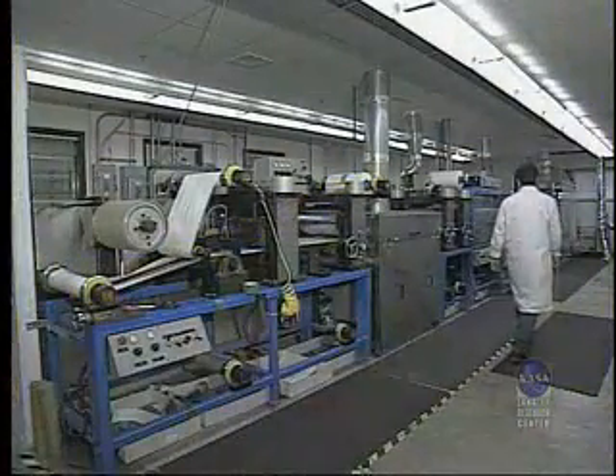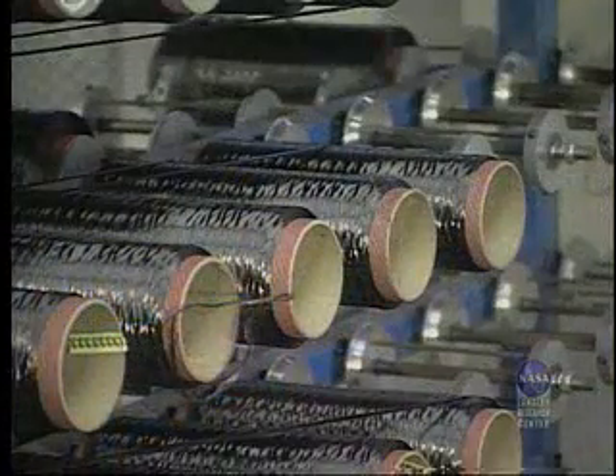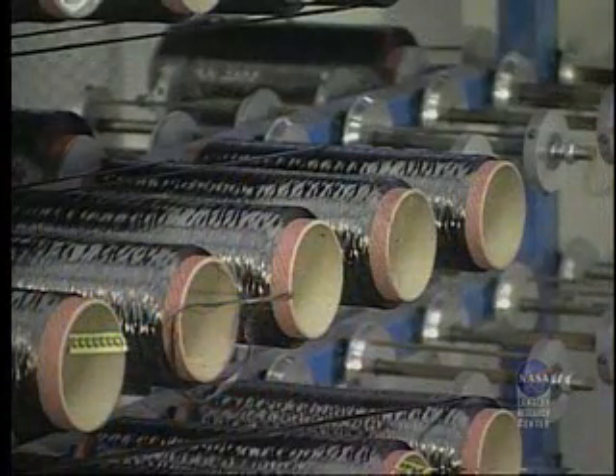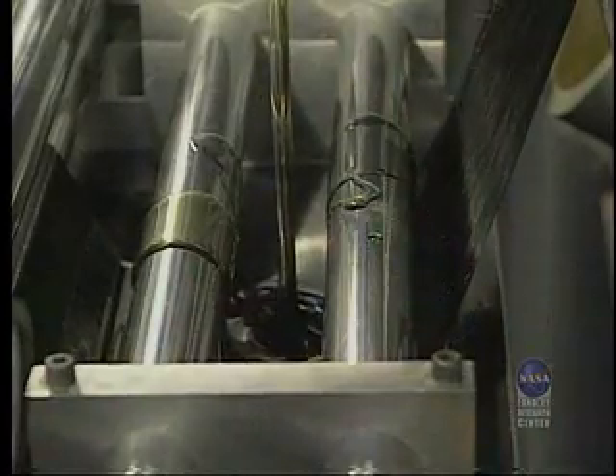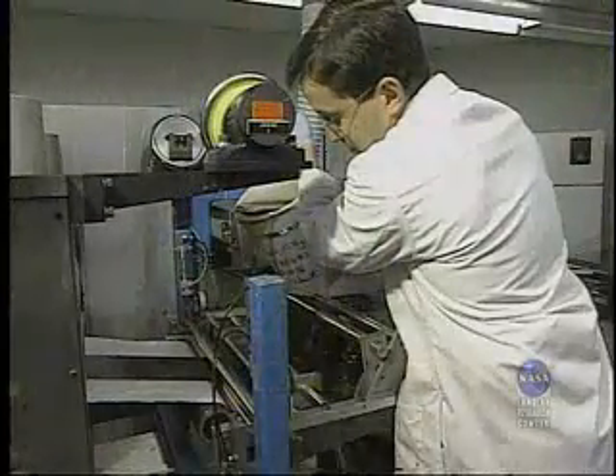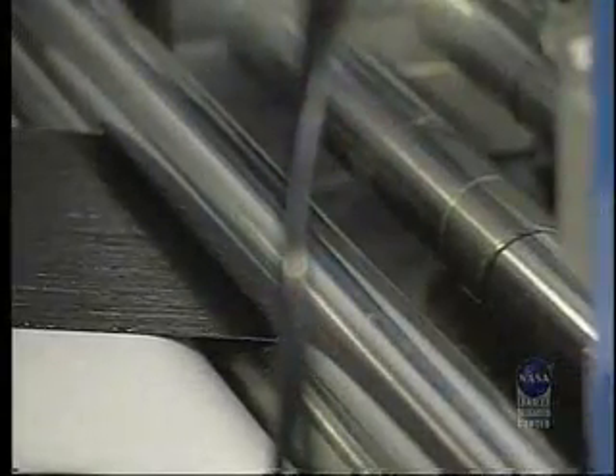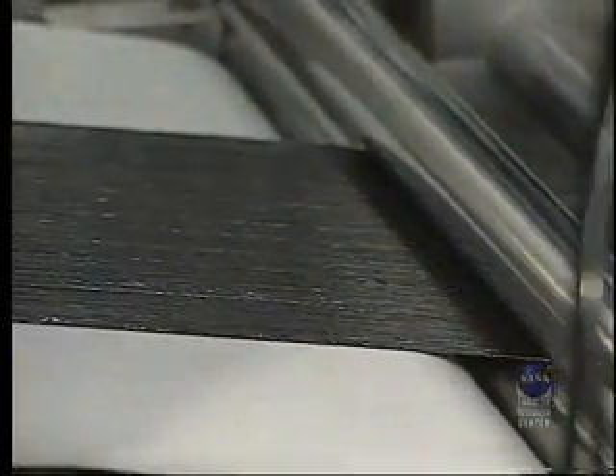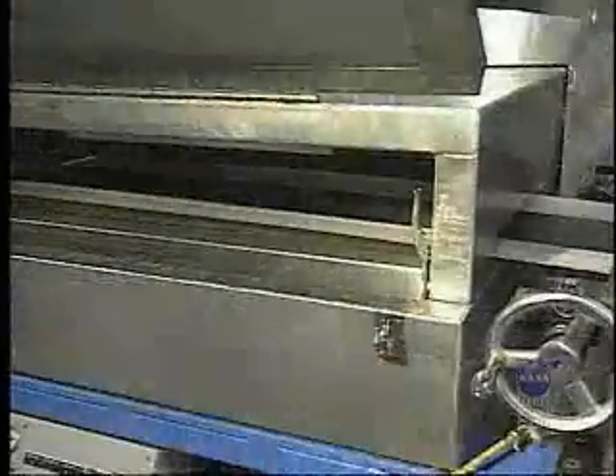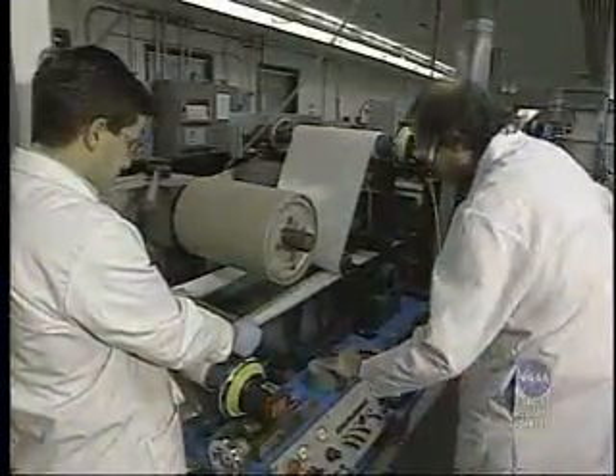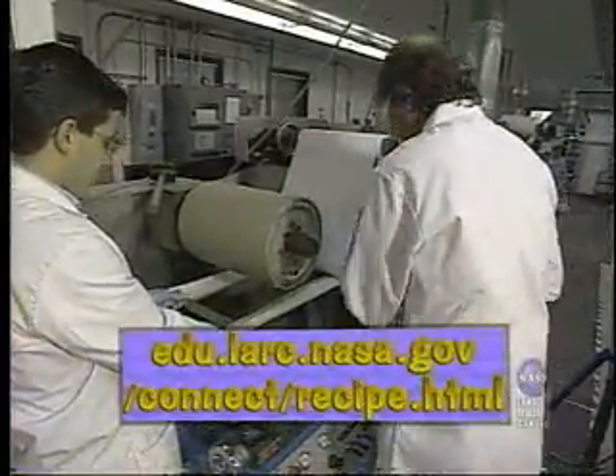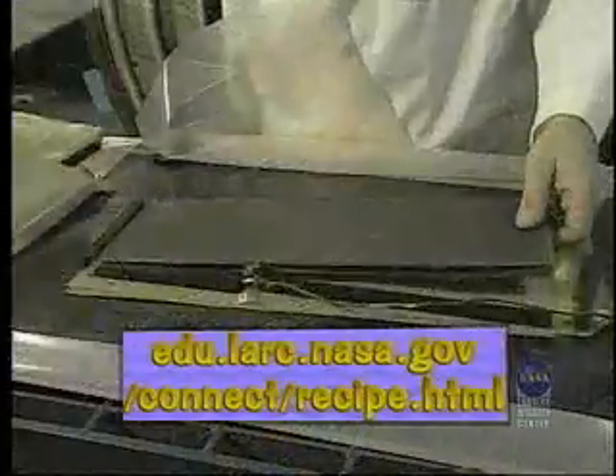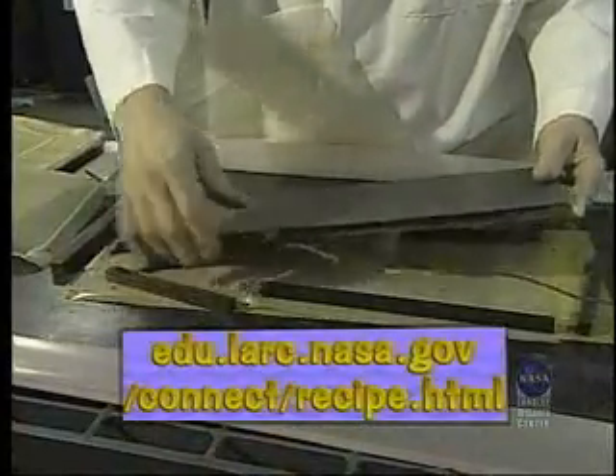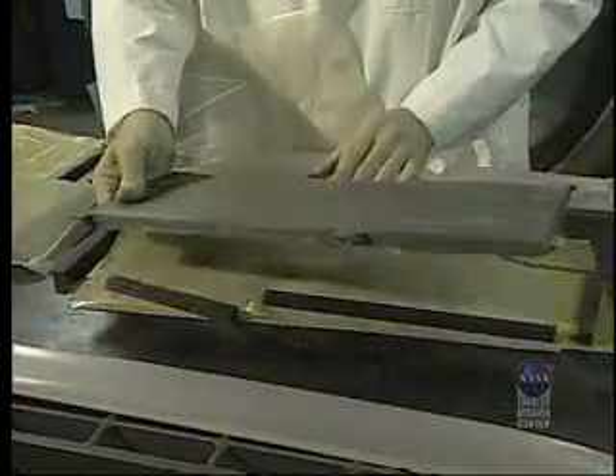To fabricate IM7 PETI 5 prepreg, many ends of IM7 carbon fiber are introduced into a dip pan. In the dip pan, the fibers go over and under a series of bars. When the resin solution is poured into the pan, the bars help force the resin into the fiber bundles. The now coated fibers exit the pan and go through a series of ovens and nip rollers. The oven and nip rollers process the material into a uniform tape that is taken up at the end. This tape is referred to as prepreg and can now be used to make composite parts. As layers of the new material are processed together, it creates a tough structure that is lighter than metal, but is strong and is stiff.